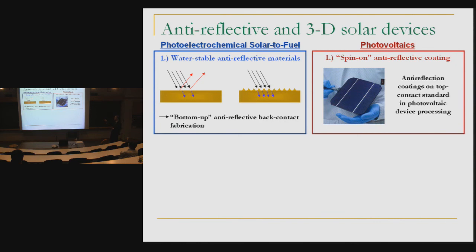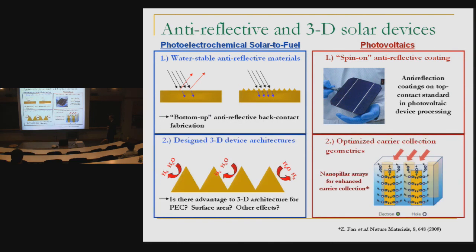But you can't really do this in photoelectrochemistry, because if you put some layer on top of the semiconductor and then put it in solution, the key point in a photoelectrochemical system is that your p-n junction is created between the interface of the semiconductor and the electrolyte, right? So you can't play the same trick with photoelectrochemical systems. In order to harvest the extra photons that would normally be reflected off a flat surface, you actually have to make the semiconductor itself texturized and anti-reflective.